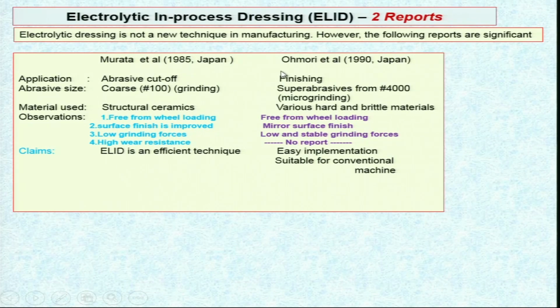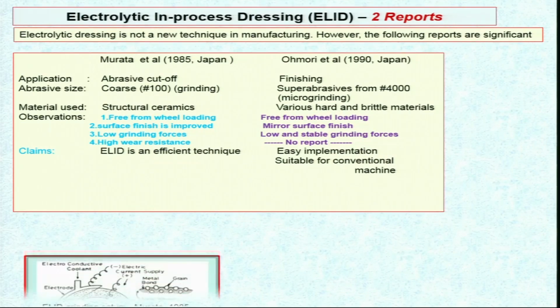In their paper. On the other hand, in 1990, again from Japan, Omori et al. published their report, and they say this is used for finishing purposes. Murata used it for cutting off purposes. Here they have used super abrasives of number 4000. They were using it for micro grinding. They used it for various hard and brittle materials. Observations: free from wheel loading, mirror surface finish was obtained, low and stable grinding forces were acting, wear resistance was not reported, and easy implementation suitable for conventional machining.